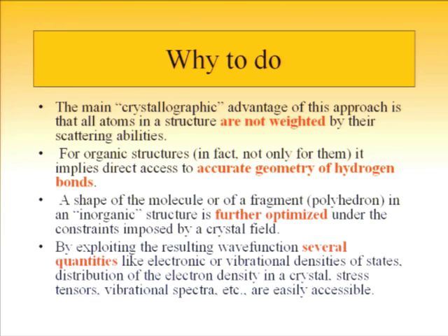And finally, when you have the resulting wave function, you can derive several quantities like electronic densities of states describing bonding details in your structure, vibrational densities of states which are of importance for those who are trying to interpret vibrational spectra. So those who are enthusiastic about electron density in crystals, yes, here it is. You can even calculate or estimate stress tensors, vibrational spectra, etc. All quantities which could be analytically derived from the total energy of the wave function are in principle available.